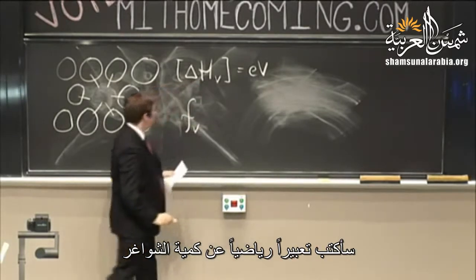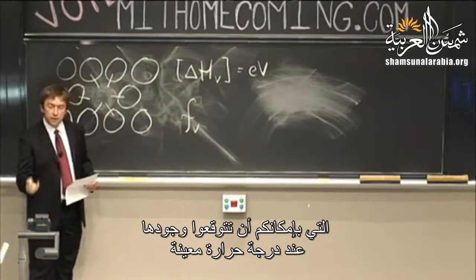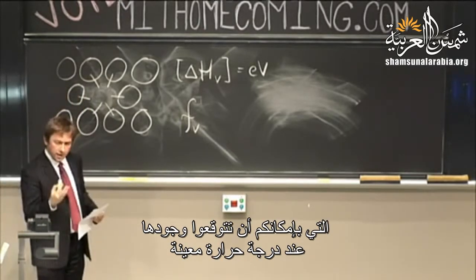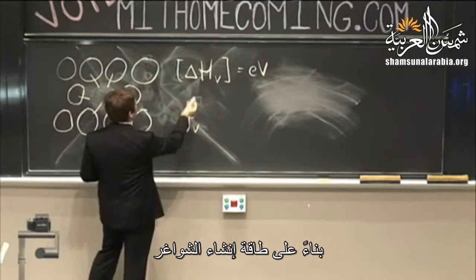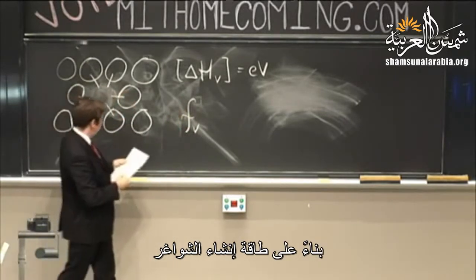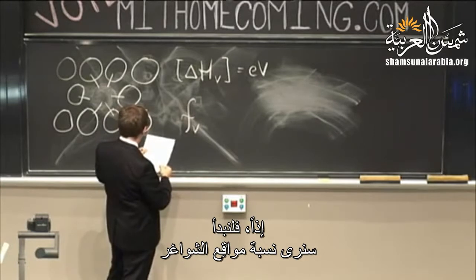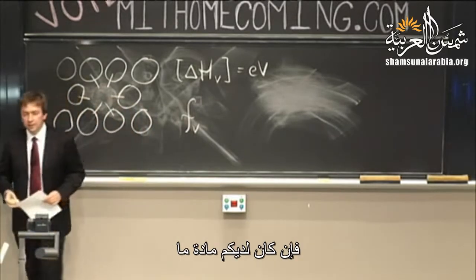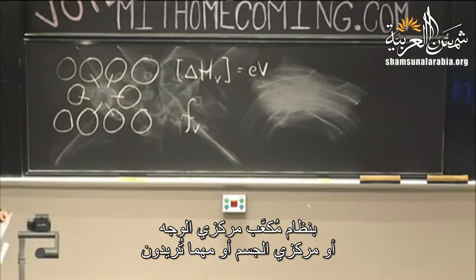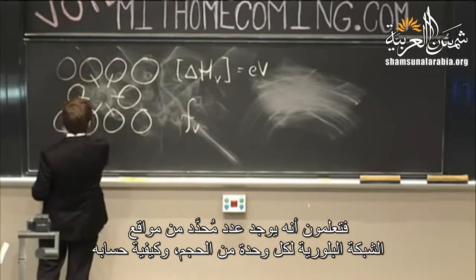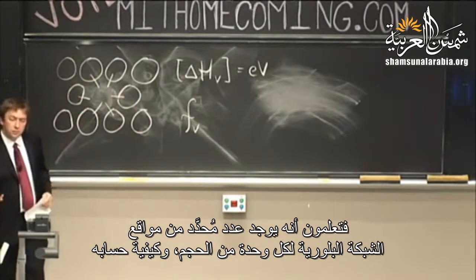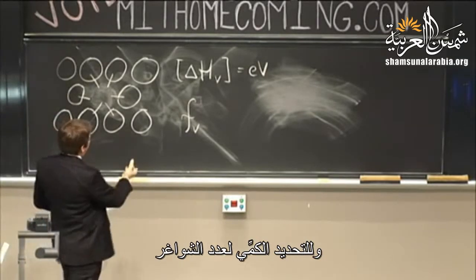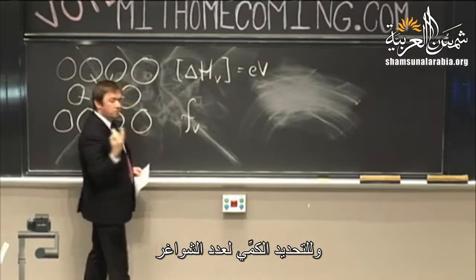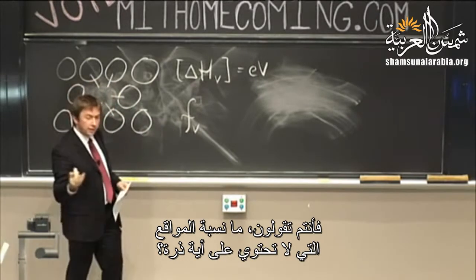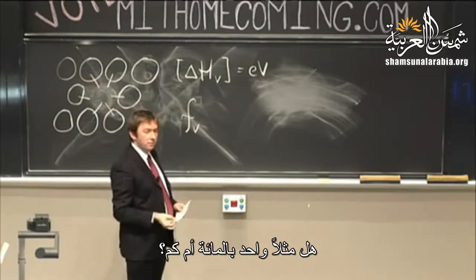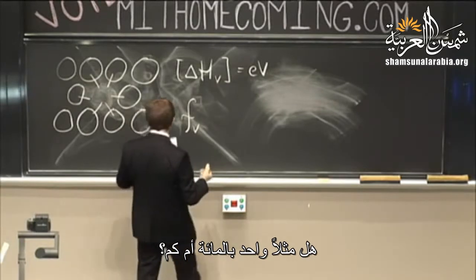So I'm going to write down an expression for how many vacancies you can expect to find at a given temperature on the basis of their formation energy, okay? So let's do that. This is going to be the fraction of vacant sites. So if you have a given material, FCC, BCC, whatever you like, you know that there's a certain number of lattice sites per unit volume, and you learn how to calculate those things. And to quantify the number of vacancies, you have to basically say what fraction of those sites does not contain an atom. Is it 1/100%, or is it 1%, or how many?